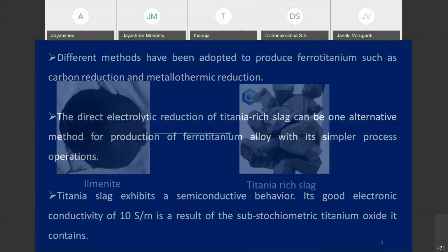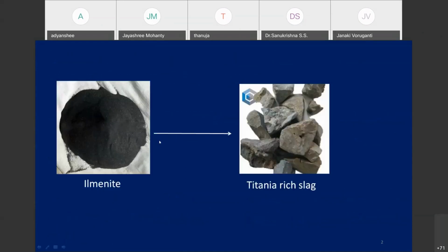You can see here it is ilmenite powder. It can be converted after plasma smelting or any kind of carbothermic reduction or metallothermic reduction. Then they will produce iron metal. Iron metal is separated, and after separation of iron metal, you are getting the titanium slag. This kind of slag material you usually produce.